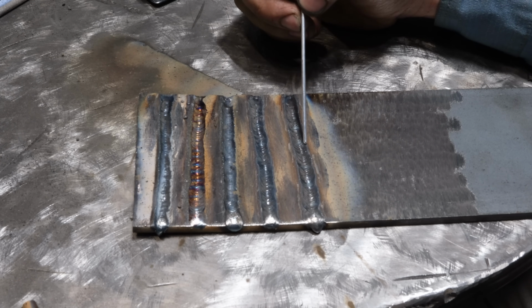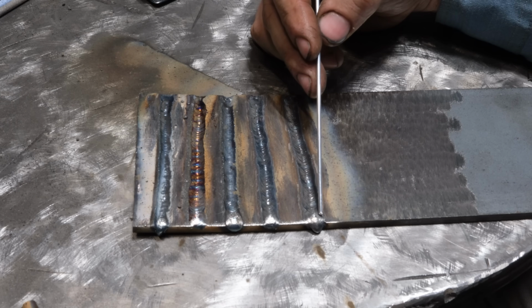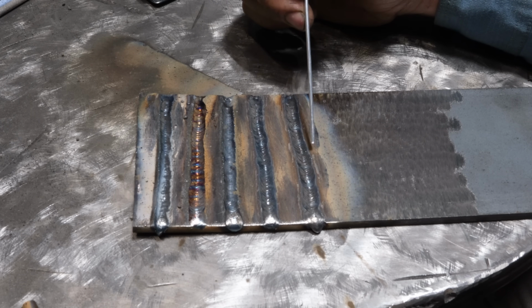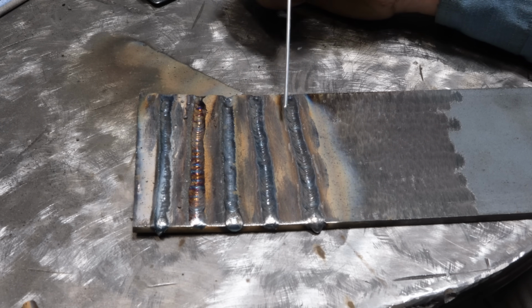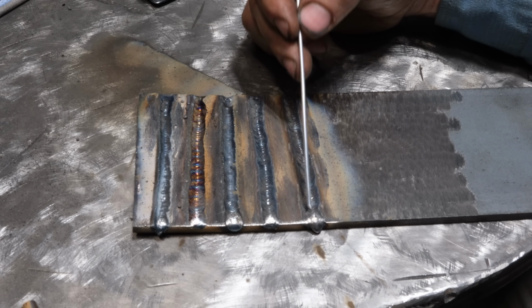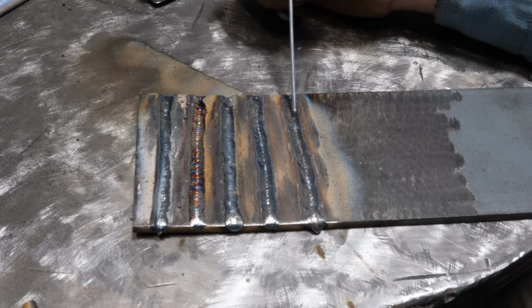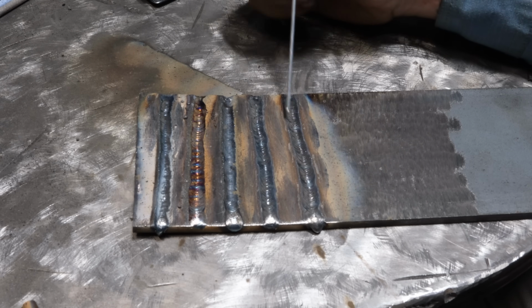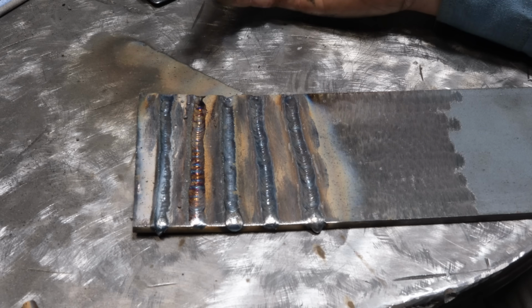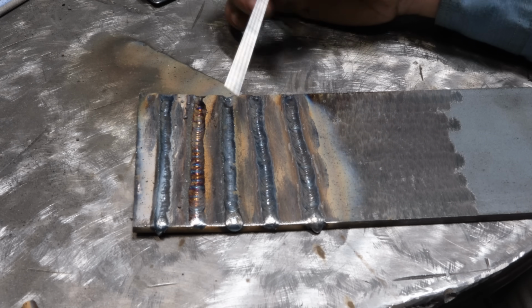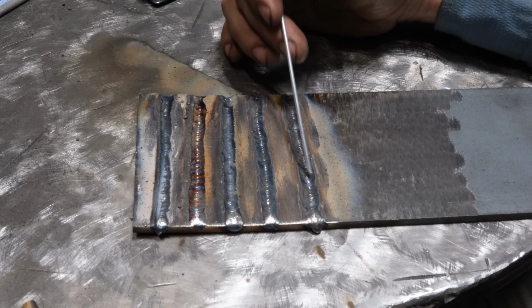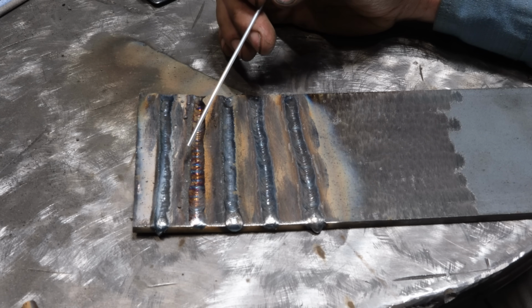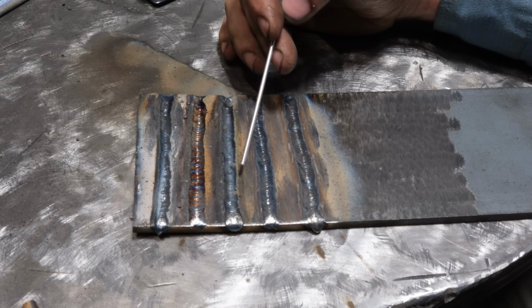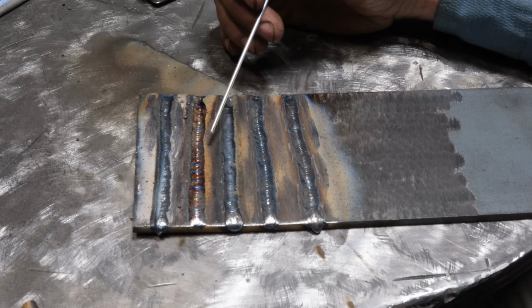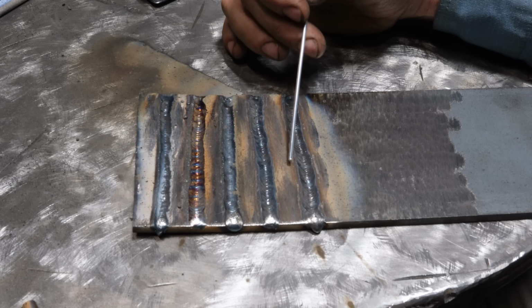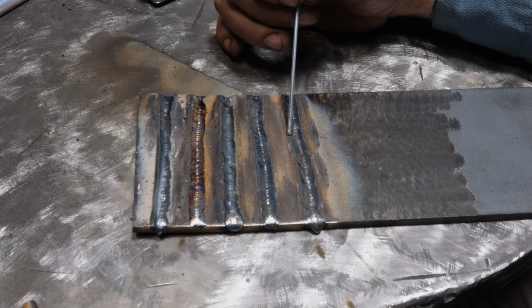And then this was the 11018. The 11018 was a lot harder for me to start. I was running at 120 amps. I would have liked to have started at a higher amperage, and I should have enabled hot start. This rod seemed to be a little bit more difficult, like I said, to start. It ran very similar. It looks just like 7018. Maybe the color's slightly different, but very similar. Now, the interesting thing was when this was cooling, I heard a whole lot of pings and pops like welds were cracking. I don't see any evidence of it on any of these, but that's generally not a good sign on mild steel to hear that.